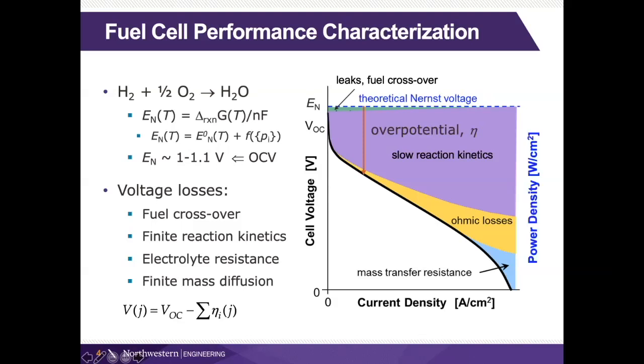Then the next thing that we'd like to characterize is the power density. And so that's simply the voltage multiplied by the current density. And so we get some plot that looks like this. Typically we operate our fuel cell not at maximum power because that would give us relatively low efficiency. So we're about here. So we get a reasonable voltage, maybe around 0.7 volts. This is usually a little over 1 volt for the open circuit voltage. The further we are from open circuit, the lower the efficiency because the larger the overpotentials.